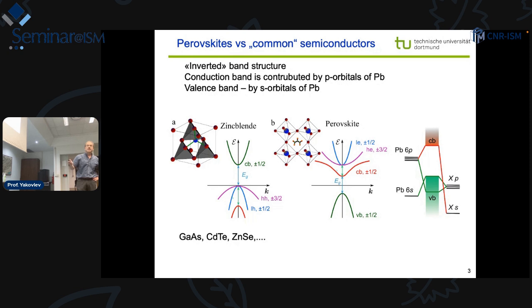The conduction band is simple with spin 1/2, but the valence band is already complex with spins 3/2 and 1/2, and there are spin-orbit states for the holes. And actually, if we're dealing with spin physics in common semiconductors, a lot of complications come from this complex valence band, because the hole states are mixed with each other, so the spin relaxation processes are very fast.